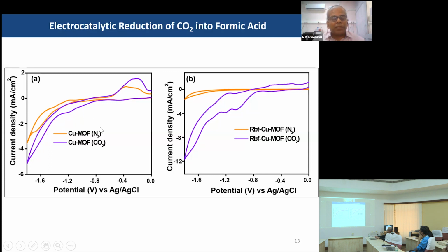When the electrolyte is saturated with nitrogen, there is still a slight increase in the current density, which might be due to the hydrogen evolution reaction. But when we used carbon dioxide-saturated electrolyte, there is no hydrogen evolution reaction; instead, the reduction of carbon dioxide happens, leading to a prominent increase in the current density.